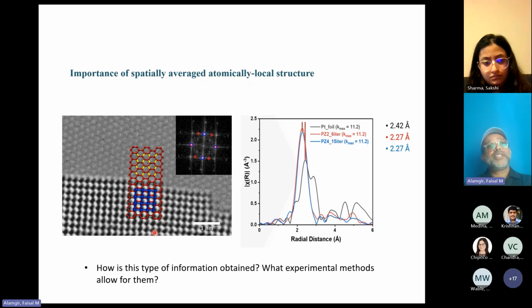And once you have these kinds of images, you can do a lot of analysis. You can actually see how the platinum atoms are templated on the graphene sheet, and you can do an analysis of how the registry happens between them. And so the point of this paper was to show that there was epitaxy between the platinum atoms and the graphene. But I want to point out something else in the title of this slide, and that is spatially averaged atomic local structure. What you're looking at here is not really spatially averaged. If you look at the scale bar here, it's 1 nanometer.